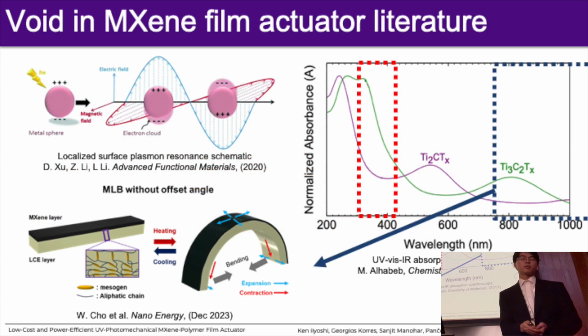Right, so how does this work, and how are people using this in the soft, mesoscale actuation community so far? The photothermal conversion in the MXene comes from the localized surface plasmon effect, which some of the researchers here presented about in other presentations. What happens is when you shine a light onto the MXene, the titanium, or any of the metal parts of the MXene resonates, creating this friction-based heating on the film. What's nice about that is that, for example, in particular this researcher from Hanyang University in Korea, when you put a layer of MXene onto any expanding or contracting materials, such as liquid crystal elastomers, you can quickly induce a heat-induced mechanical bending, let's say through an interfacial stress.